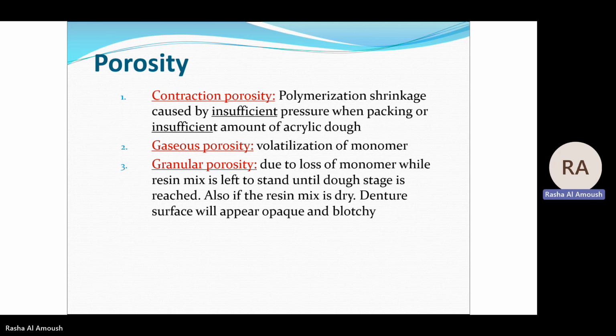As we said before, if you reach the boiling point, for example, of the monomer, you will get some gaseous porosity. So we have different types of porosity, starting with the contraction porosity. Contraction porosity happens due to polymerization shrinkage, if you have insufficient pressure when packing or insufficient amount of the acrylic dough. Gaseous porosity happens due to volatilization of the monomer if you exceed or reach the boiling point of the monomer. Granular porosity is usually due to the loss of the monomer while the resin mix is left to stand until the dough stage is reached. Also, if the resin mix is dry, then we will get some granular porosity. The denture surface here will appear opaque and blotchy.